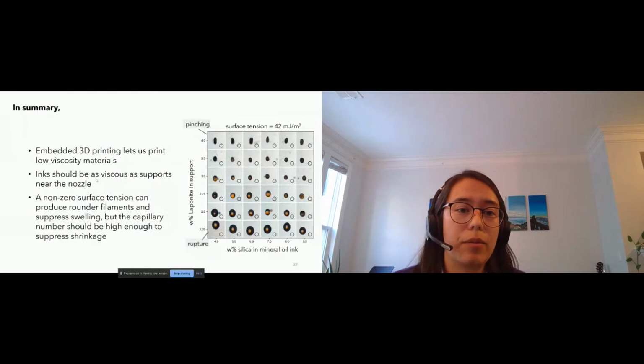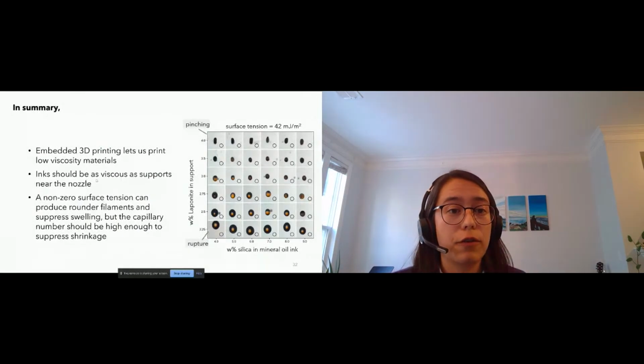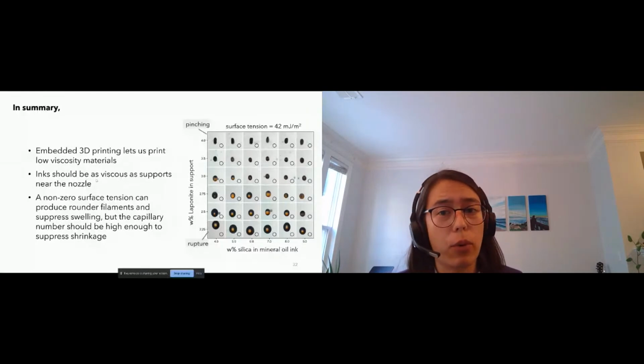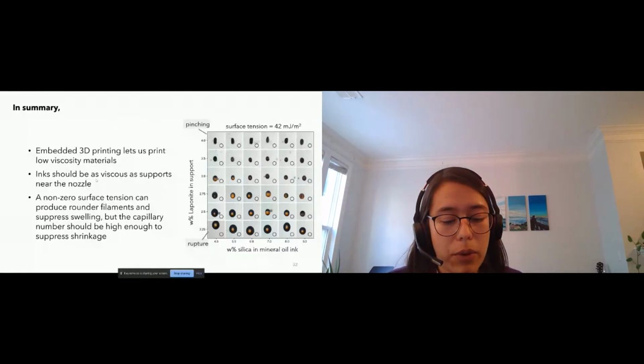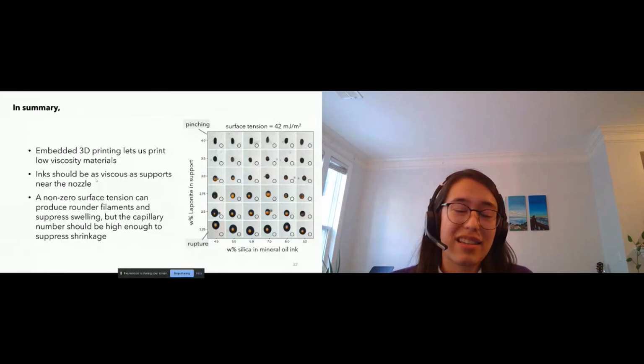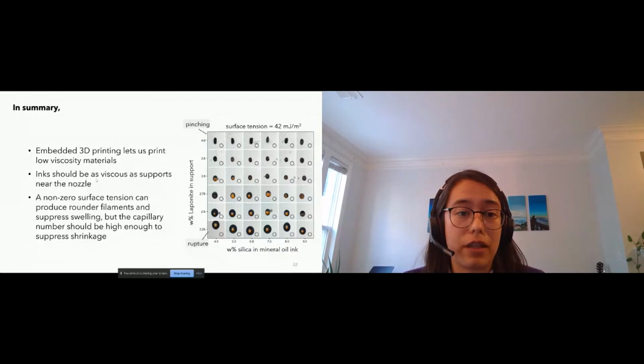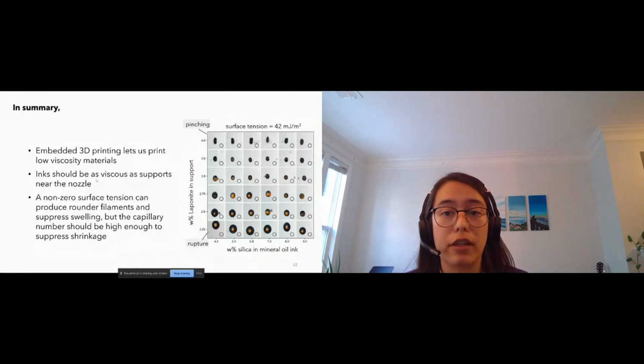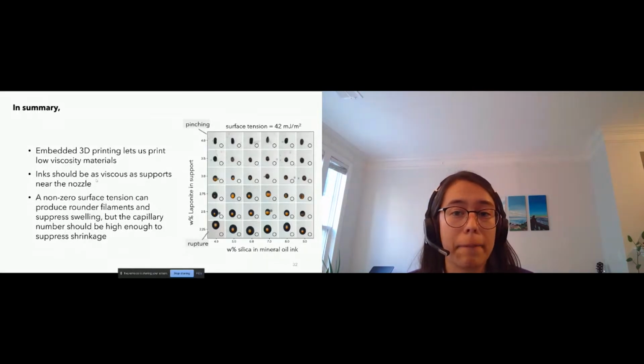So to summarize, embedded 3D printing, or embedded direct ink writing, is a really useful tool for printing low viscosity materials, and really has a lot of promise in the bioprinting space because bioprinted materials or biomaterials tend to be low viscosity and have specific properties that you're looking for when you're printing cells and things like that. If you're choosing a support for embedded 3D printing, you need to make sure your local support viscosity is slightly lower than your local ink viscosity near the filament. And finally, a non-zero surface tension can be useful if you want to produce rounder filaments and suppress surface roughness and swelling, but you need to choose a capillary number that is high enough to suppress shrinkage.